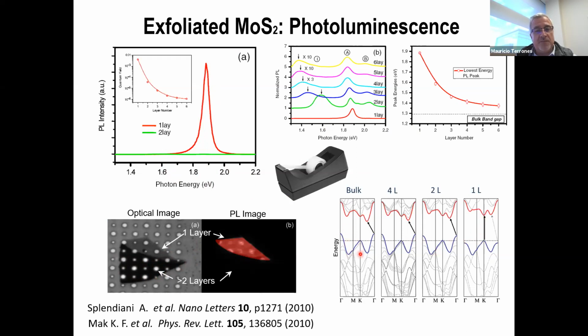So what happens in the band structure is that when you have the bulk, you usually have an indirect band gap. This is the K point. So you usually have an indirect band gap. As you start reducing the number of layers, this indirect band gap becomes larger and larger until the direct band gap at the K point becomes the shortest one. So that means you have a transition here, and you have a direct band gap here, and then you have this PL signal coming from the monolayer. And that's something that's beautiful in these systems that are semiconducting. And then you can see easily a monolayer compared to 2 layers or 3 layers. So this is what's very, very important.